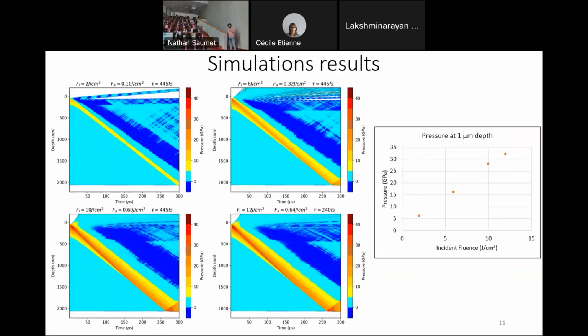So let me now present some results from simulations and experiments. So first, these are pressure maps obtained from TTM-MD simulations, where we can see, so here at the top is the surface, and then we can see as a function of depth and time the evolution of the pressure wave. So here we have 4 different fluence from 2 joule per centimeter square to 12 joule per centimeter square. And we can see as a result of this that the pressure as a function of the incident fluence is almost linear. So this will lead us to think that the created residual stresses below the surface will be a linear function of the incident fluence.